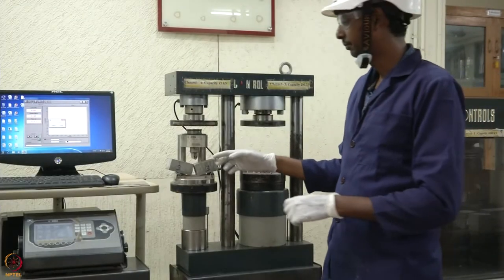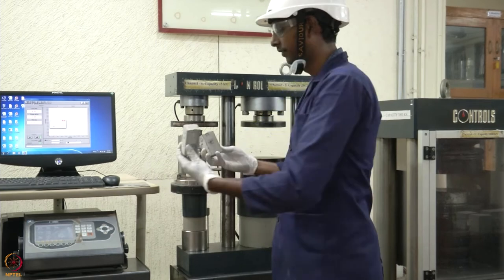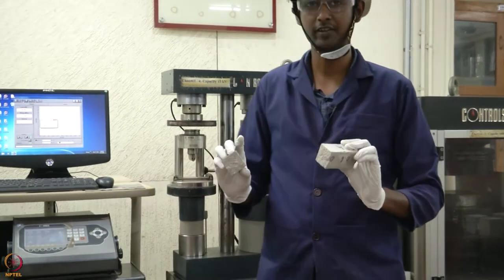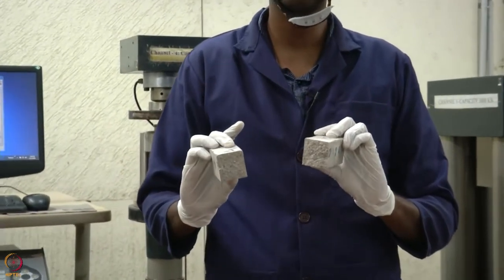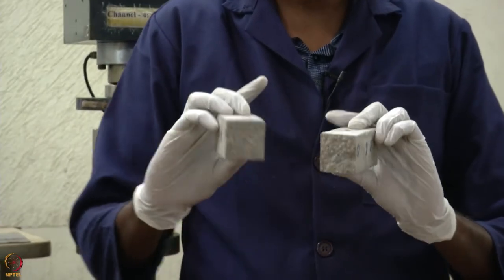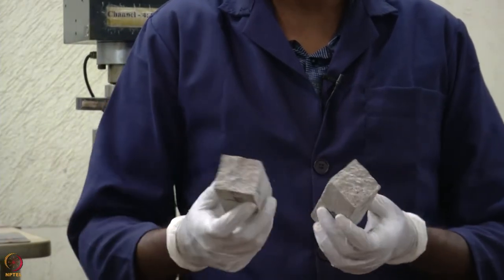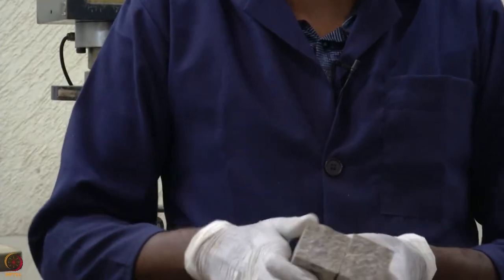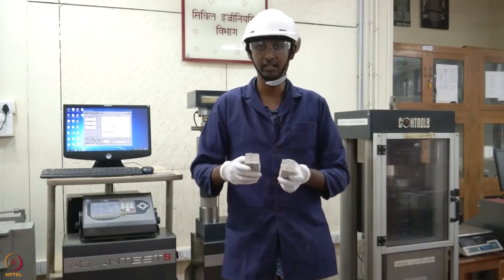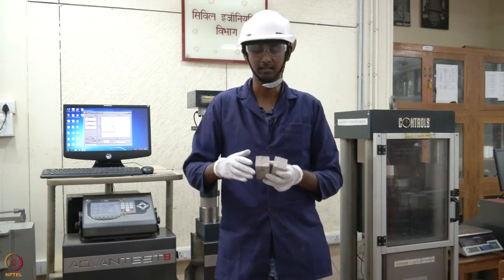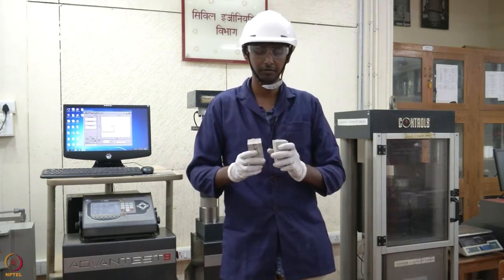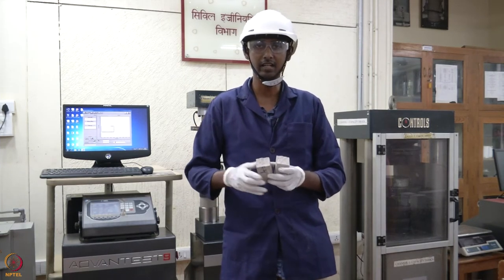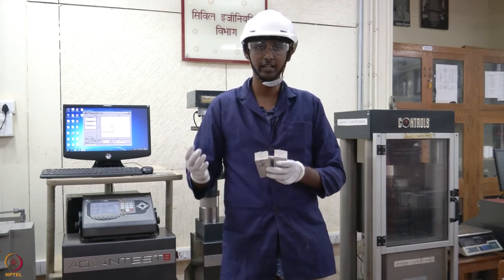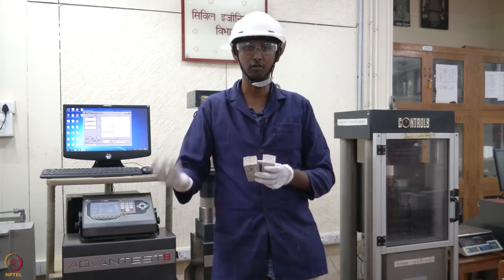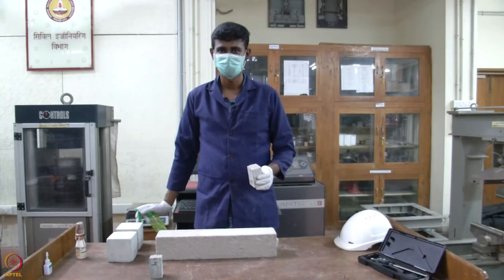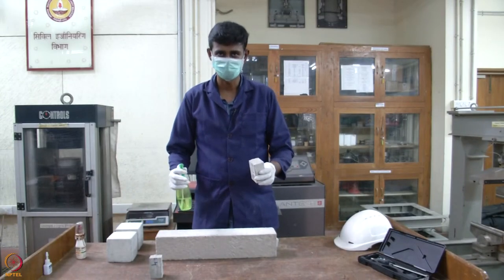So, after the prism is broken, we are just going to spray the phenolphthalein indicator over this. This is the freshly broken surface. This kind of breaking is preferable to saw cutting, just to avoid the calcium leaching which could possibly occur during the saw cutting. The carbonation front will get disturbed when a saw cut is done. The spraying of the indicator should be done at once to avoid any other external carbonation which could possibly occur. So now I am going to spray the phenolphthalein indicator over the freshly broken surface.